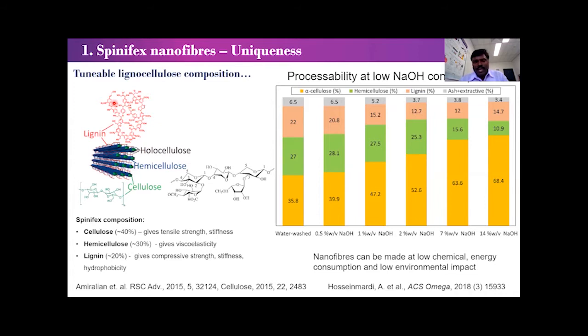Especially non-wood biomass sources have a higher amount of hemicellulose, which is a thermoplastic polymer that makes the fiber tough and flexible. So you can make a tough paper from this nanofiber. We invented this fiber in 2013. Because I come from a background in CNC, which is rod-like nanocellulose, when we saw this one we were so excited about the toughness we could get with the nanofiber. That's where we went into protecting the IP.